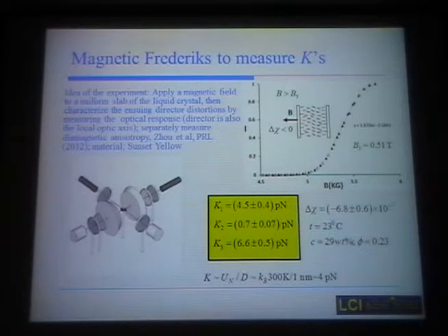If you read de Gennes's book, you would find a very simple explanation of the range of values of the elastic constants in normal liquid crystals such as 5CB. De Gennes said, look, the nematics melt into the isotropic phase at temperatures that are not that far from room temperature, right? 5CB, for example, melts at around 36 to 37 degrees, depending on the purity. And there is this length of molecules in the liquid crystals.